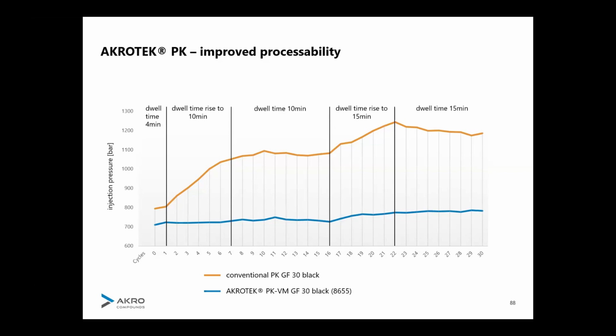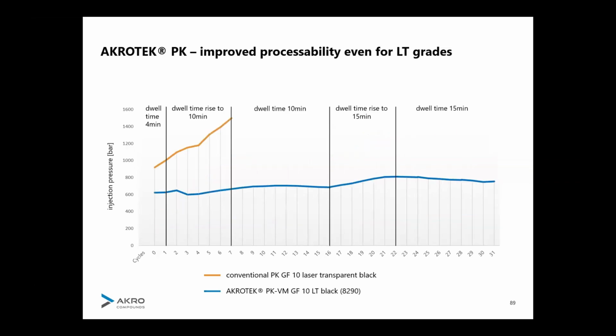And so we were able to develop our own stabilization package for polyketone. As you see, we could say it decreases a bit, but compared to an unstabilized polyketone for the processing, we were really able to reduce this behavior. And that is really well appreciated by customers. We always see it when we attend trials. We say, okay, now stop the machine for 10 minutes. Oh, we are not going to do it. And they're really surprised that it works now. And this is not only working for standard grades, but also for example for the laser transparent grades we also use, especially in these kind of thermal control units.